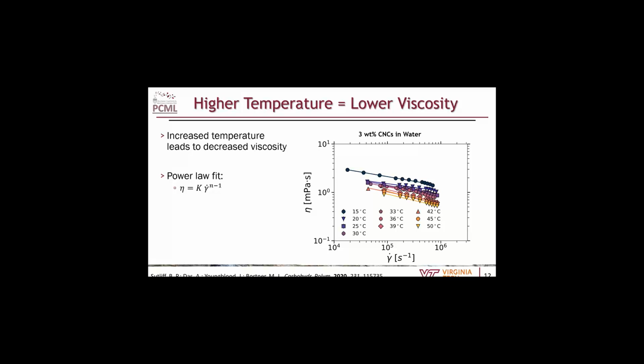Anyone who saw the last talk will recognize the power law fit that we were able to fit to this, where we've got our flow consistency index and our flow behavior index. With higher concentrations, you have a higher flow consistency index, and with lower temperatures, you get a higher flow consistency index, and you also tend to have a larger flow behavior index.